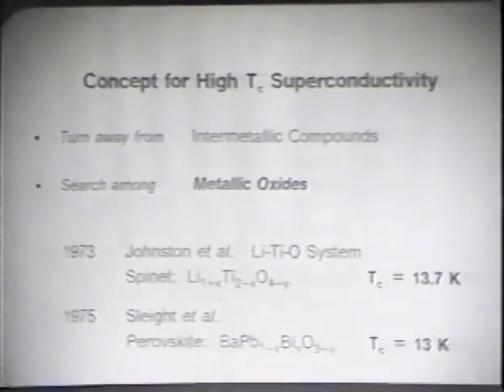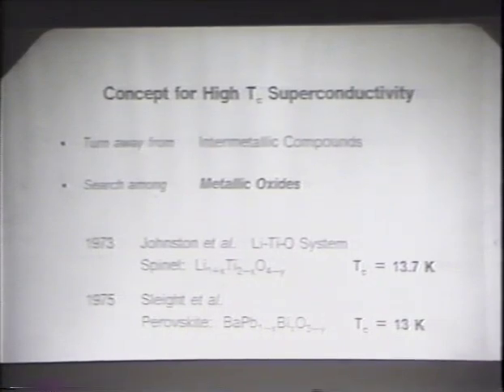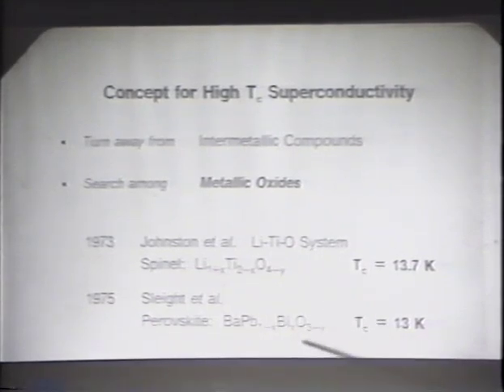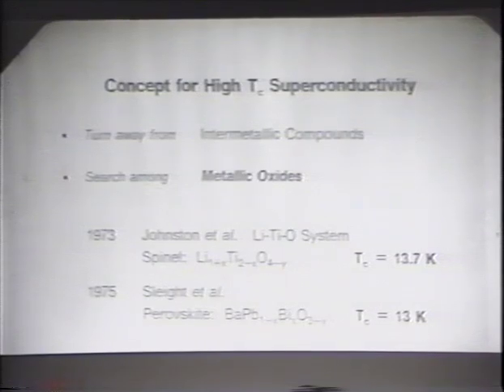Now, how did we find this material? Well, we had a concept for high TC superconductivity. Namely, I had come to the conclusion that one should radically abandon intermetallic compounds. There had been many groups who had tried to improve the TC in this area, but do a search in metallic oxides. What was the rationale of doing that? Well, in 1973 at San Diego, they found a TC of 13.7 degrees Kelvin in the lithium titanium spinel, and 2 years later at DuPont, Sleight and co-workers found in the barium lead bismuth oxide a comparably high TC.